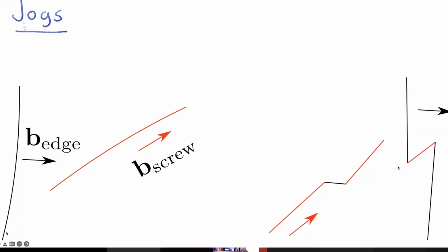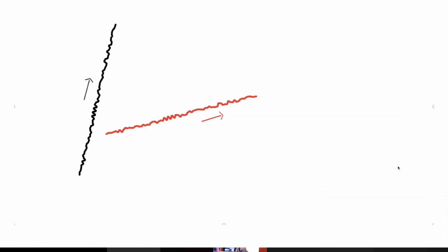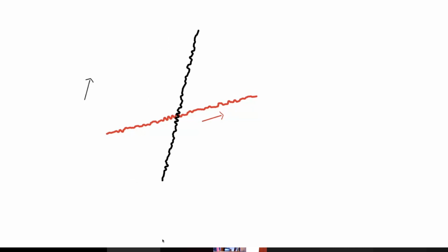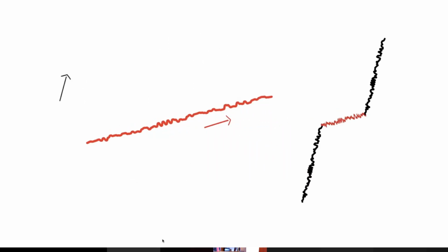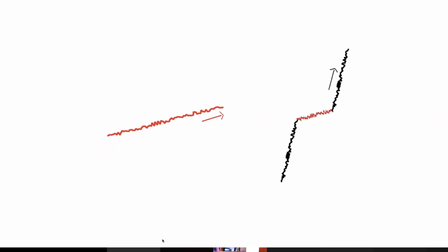So what happens is that these dislocations interfere with each other and create steps which become sessile. That means they cannot move without diffusion. And that's a problem for martensite, okay? So if you look at a very high resolution at a martensite-austenite interface, then you will only see one set of parallel lines, because having more than one set means that you would get interference and the structure of the interface would become sessile.